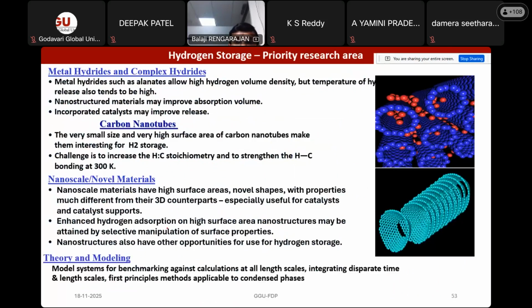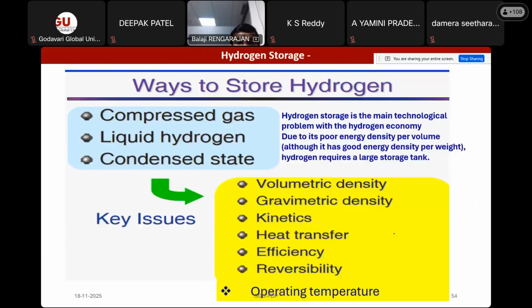So in that porous material, if you can accommodate hydrogen gas at an elevated pressure and temperature, it can occupy the voids of the material. And if you give the same temperature and pressure, you can get back the hydrogen whenever it is required. So that's a carbon-based porous material. It's also upcoming to use as a very good hydrogen storage material.